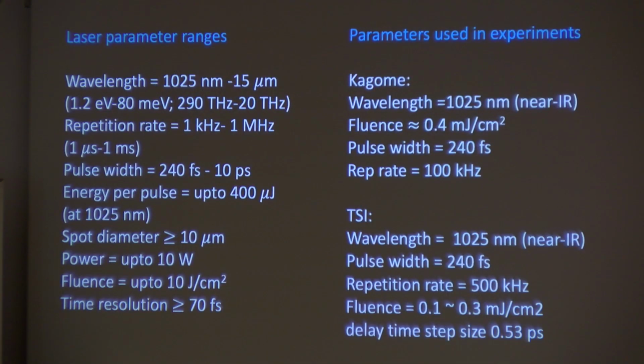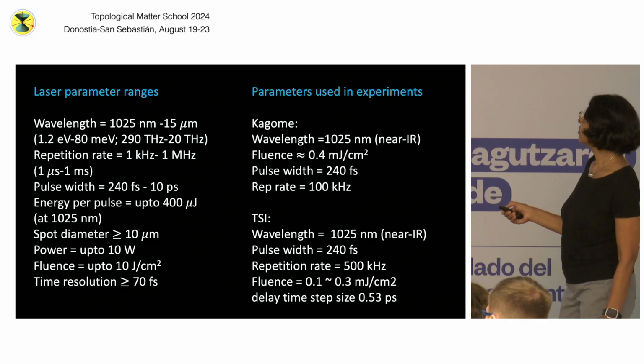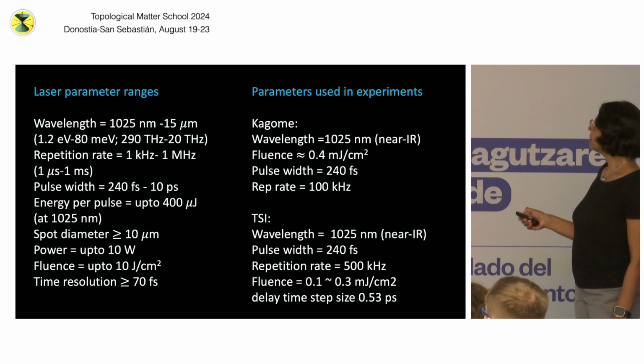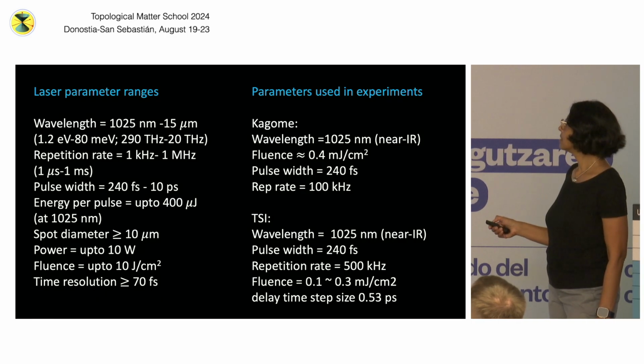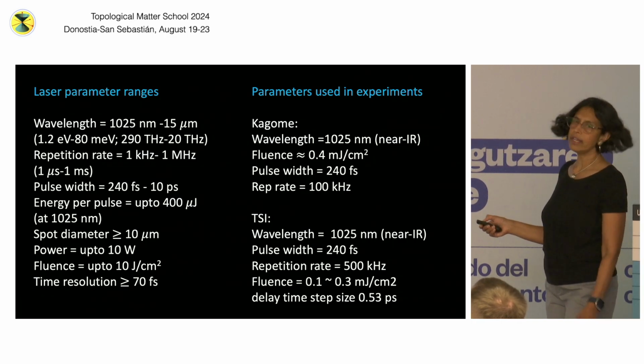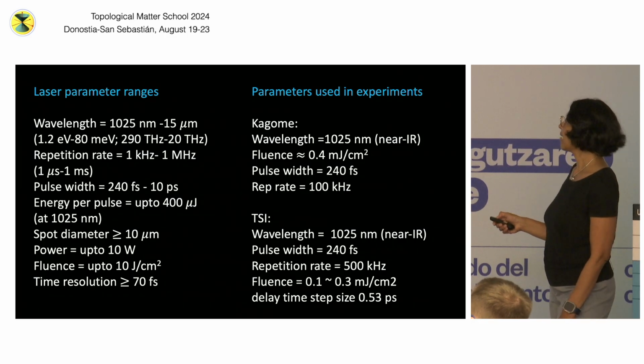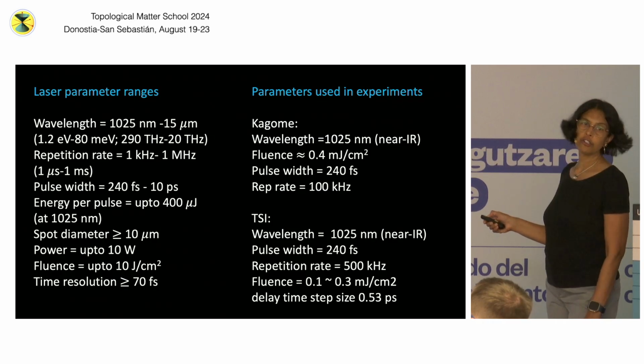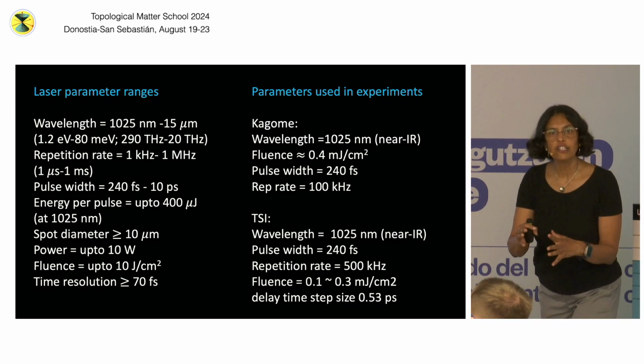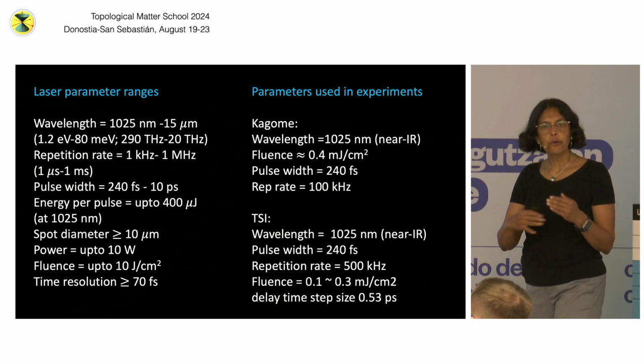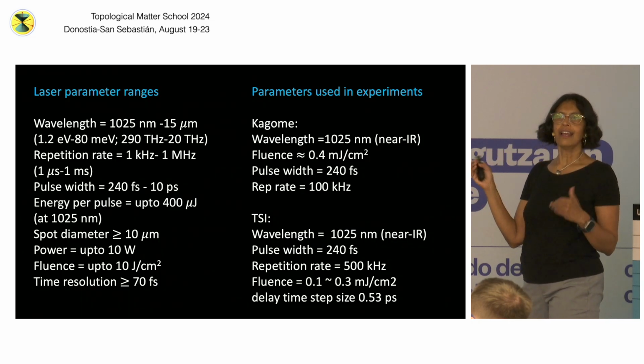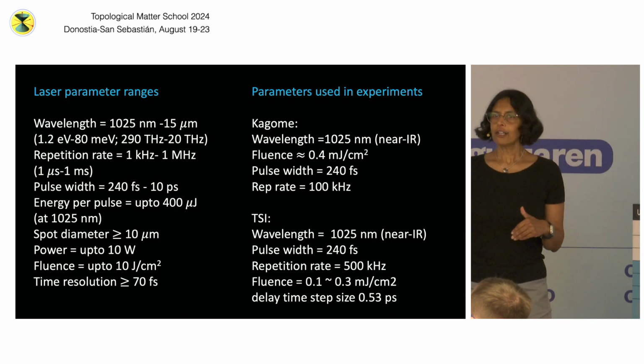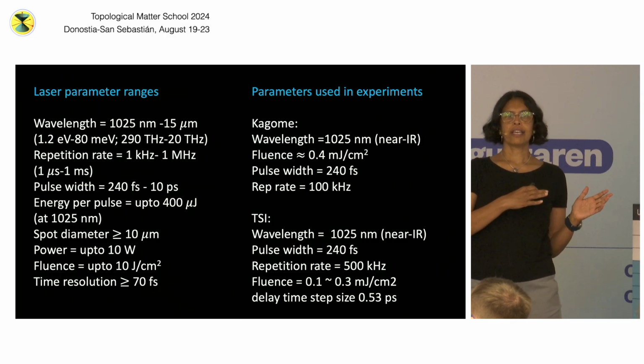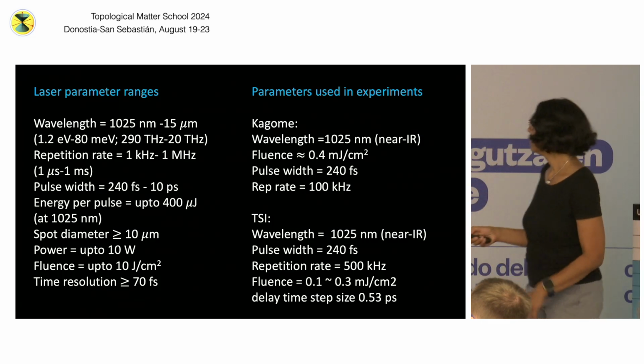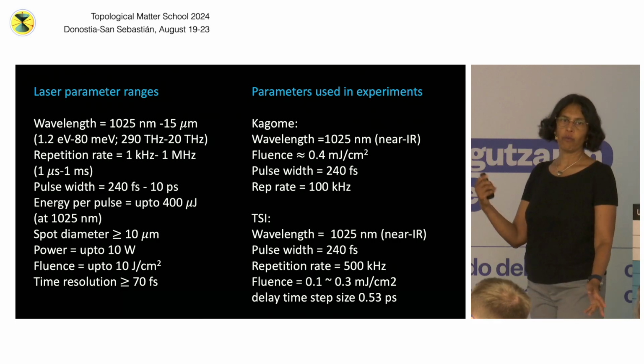All right. So this is what we have right now. This is the range of our energy, right? We have an eV or more. We can use different lasers to get higher. But the lowest right now we can go to is 80 meV for excitation. That doesn't mean we cannot probe, as you will see. It's really interesting. We can probe much sub-meV energy scales, even though we're exciting the system with 100 meV or 1 eV light.